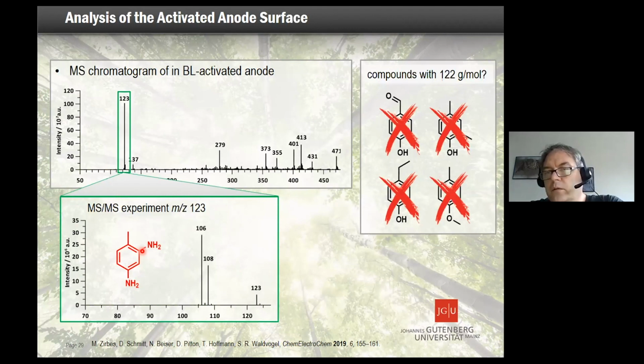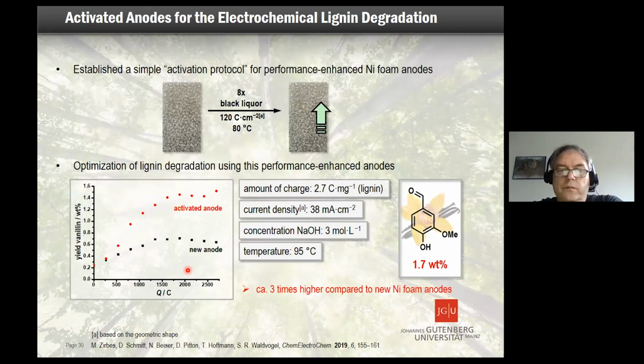It could be maybe a cross-contamination from other laboratory experiments. But it turns out it only appears if you have the black liquor in an undivided cell. Most likely it comes from a phenolic precursor, and it generates the system. By MS/MS experiment, you could easily show that this definitely forms in the system. And if you add this specific compound to the mixture, you have the same effect as the pre-treatment with black liquor. Therefore, you see what we call the activated anode here below, and the red spots. It's much better, and therefore it makes sense to add it.